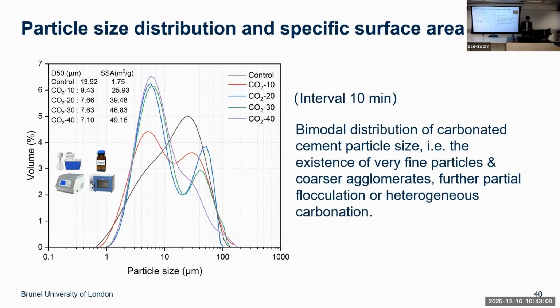Generally, we get medium particle size. We found that 20 minutes, 30 minutes, and 40 minutes give a similar kind of particle size. Over 40 minutes is better, even smaller, but it could also have consequences. For surface area, 30 minutes has a general particle size close to 20 minutes, but its surface area is much bigger than 20 minutes and close to the 40 minutes injection. So we think 30 minutes is good enough, and later research focuses on 30 minutes injection.